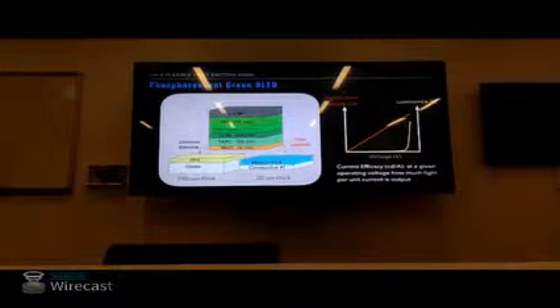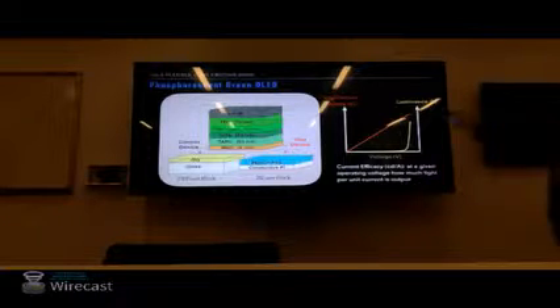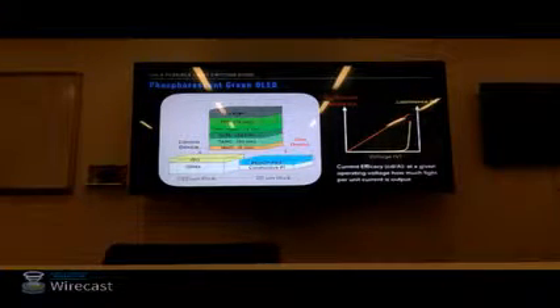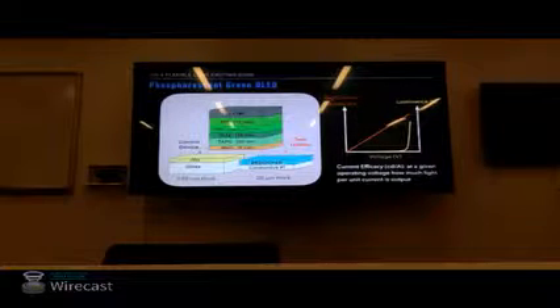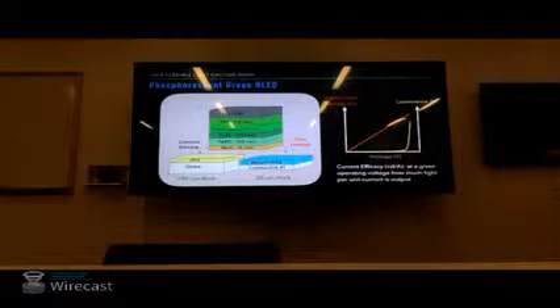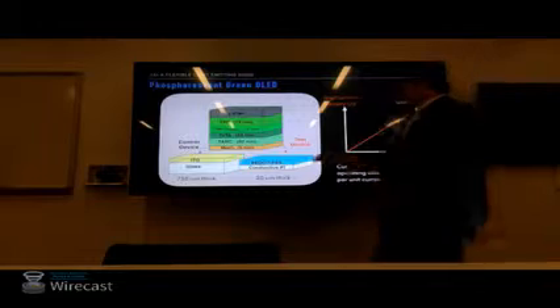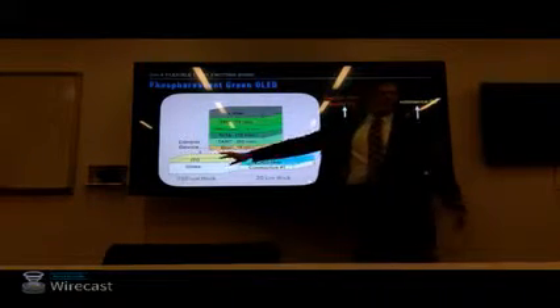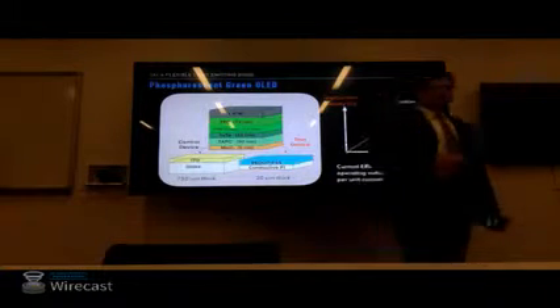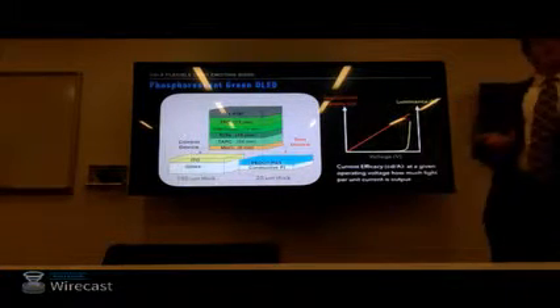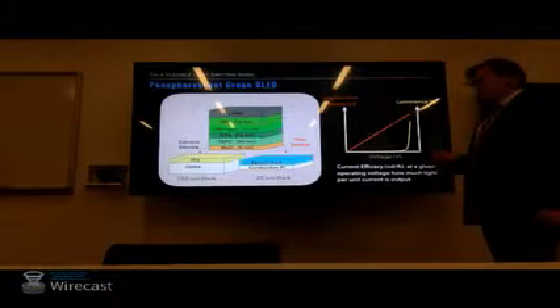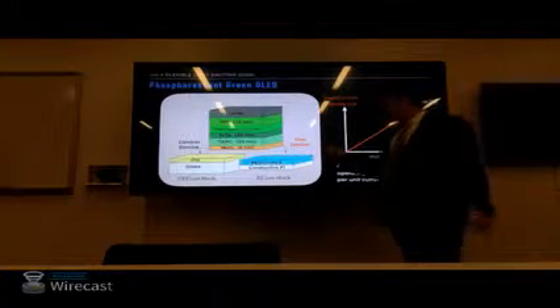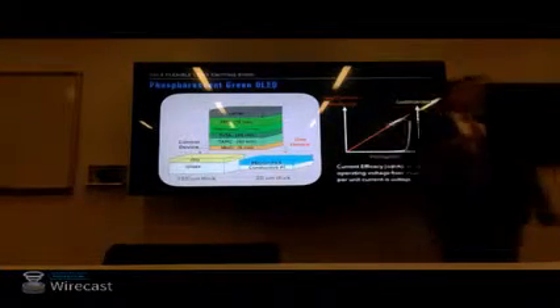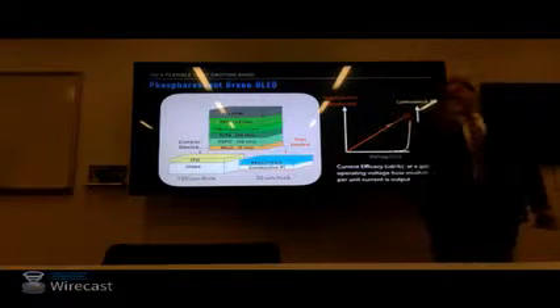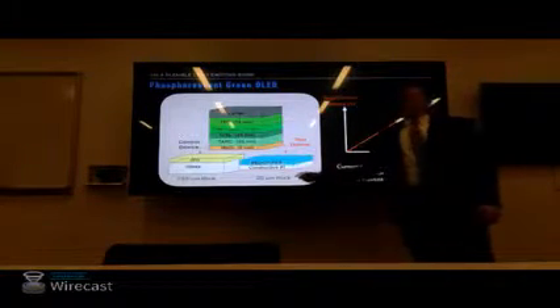So let's move on to our real device. So here are compact representations of those long, ugly organic names I had in the slide where we introduced it. And now we're going to, as I said, challenge the champion transparent conductor, ITO. Our control device is ITO on glass. That device is going to be about 750 microns thick. That's the glass, most of it. If we replace that now with our transparent polyimide, which we can use again as the electrode and the substrate, we have about 20 microns thick.